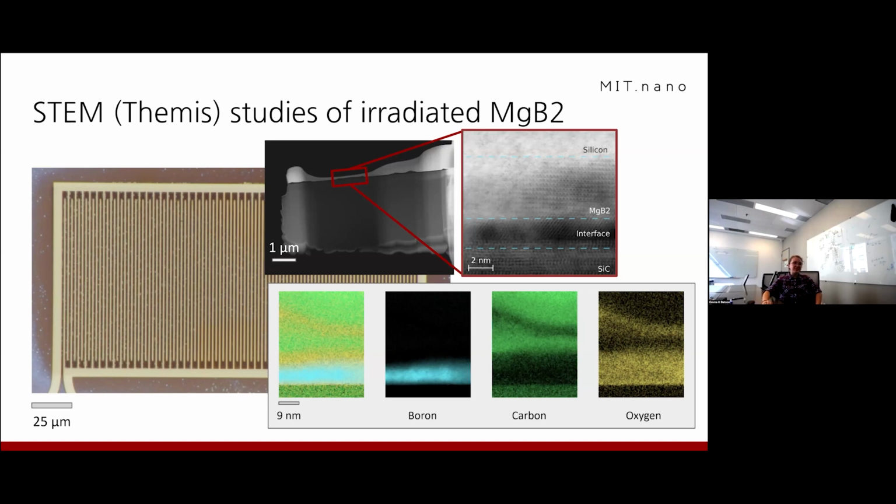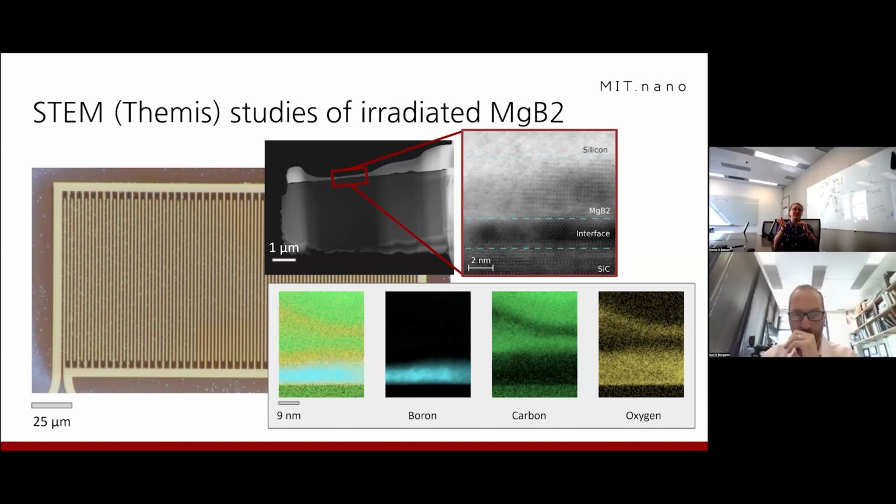Yeah, so it's a little hard to tell. Unfortunately, the EELS detector is a different detector than the one we get these really nice images from. So I don't have anything that quite exactly lines up these single atomic resolution images with EELS in particular. I believe that based on the scale of things, the magnesium diboride layer was quoted at being 7 nanometers thick. So I think that the interface layer has to be affected by magnesium diboride. Otherwise, we're kind of missing some material.